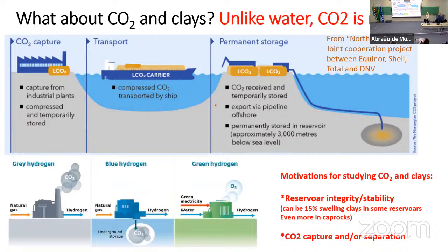The other thing which I'm more interested in is, can clays be used as a material like zeolites or MOF materials or other materials that people study for CO2 capture or separation? Meaning, for instance, I will come back to this, can it be used in blue hydrogen processing? Blue hydrogen is hydrogen produced from natural gas, methane. So you mix that with water, you go through some process, and out comes a mixture of hydrogen and CO2. Then the goal is to use hydrogen to run your car or airplanes. But you need to separate the CO2 from the hydrogen. So you're looking for materials that capture CO2, but not hydrogen, in this process.